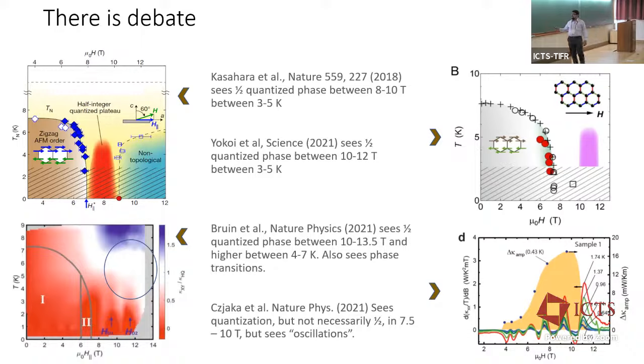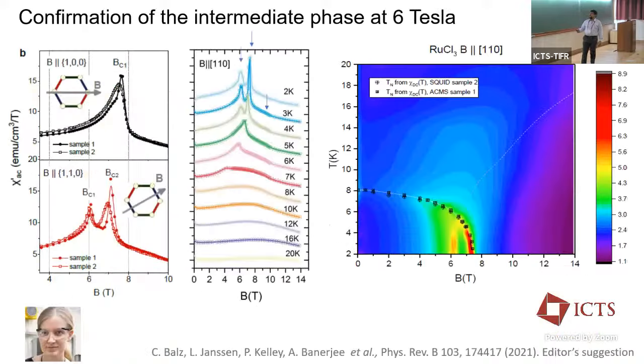And then none of that matches some of the measurements of thermal conductance in our samples by Nai Phuan Ong's group in Princeton, where we see what we think are very regular quantum oscillations. Now, the Max Planck group doesn't believe that these are quantum oscillations. They think that these are phase transitions, while we think that these look very regular. So there is a whole debate right here, and we are trying to see if there are differences in samples which are leading to this. But anyway, we were pushed to understand the material better.